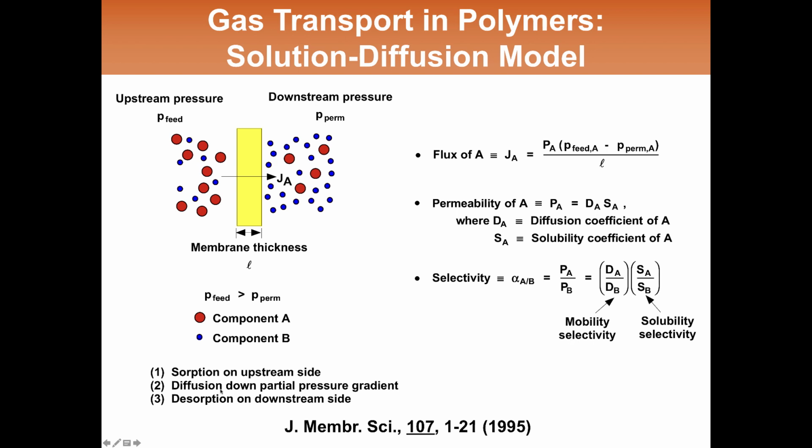And the rate limiting step in that diffusion is the slow segmental dynamics of the polymer chains that I showed you with the brief movie of hydrogen diffusing through polysulfone. The polymer chains are moving slowly, and their random thermal motion gives rise to local gaps in the polymer matrix through which the gas molecules can execute diffusion steps. And so depending upon how far apart the polymer chains are or how rapidly they move, you can change diffusion coefficients by orders of magnitude.